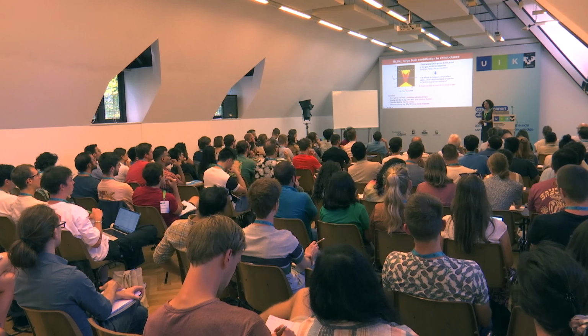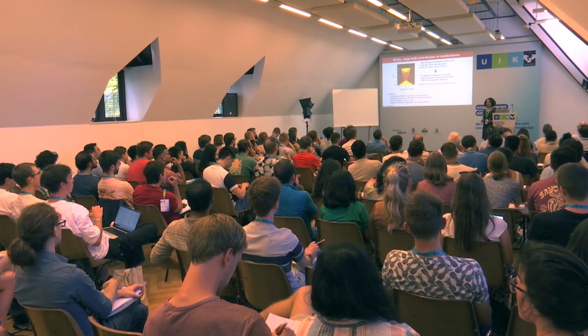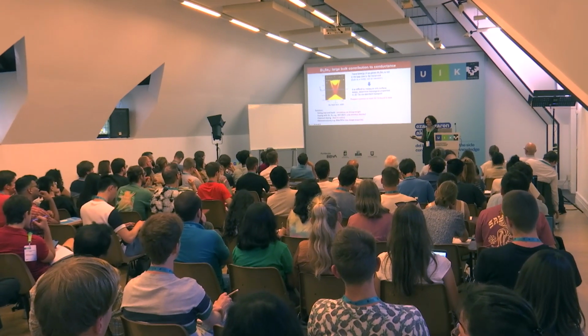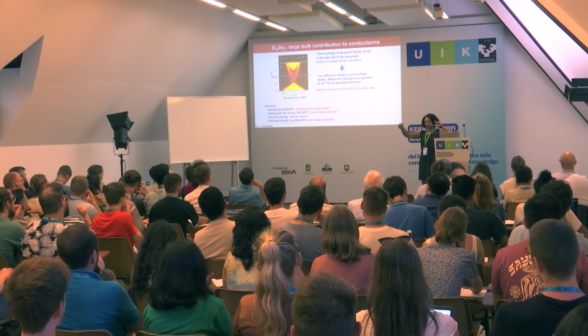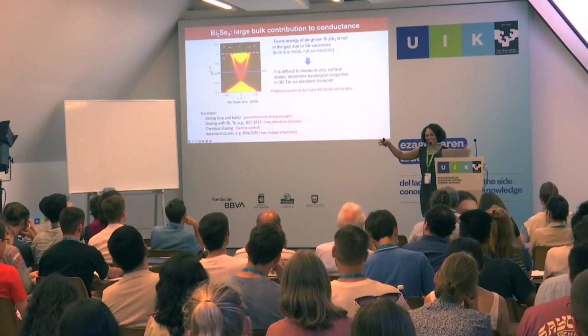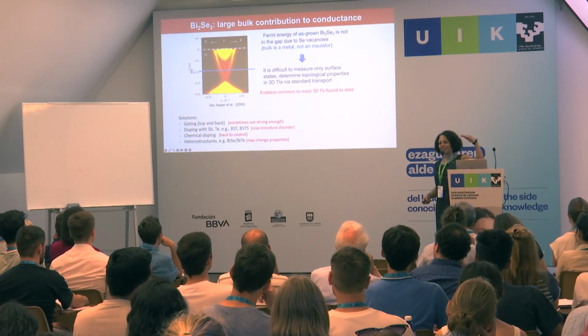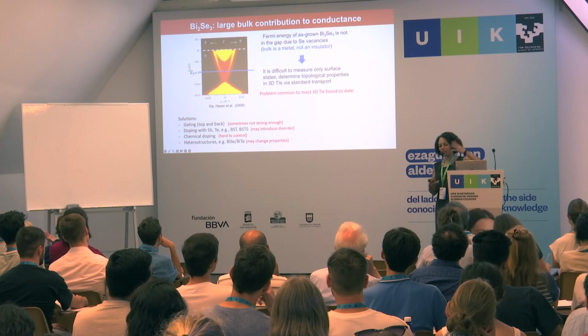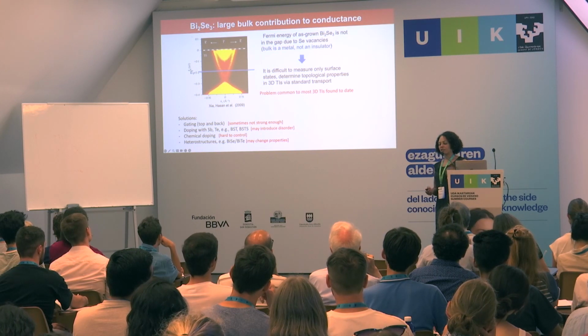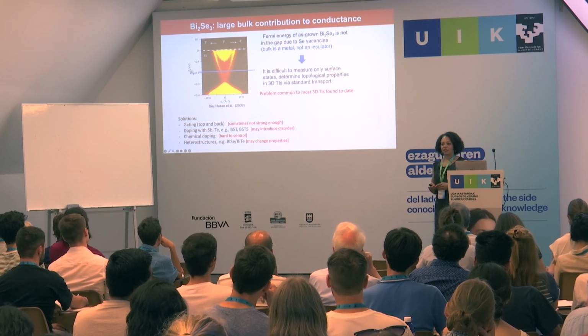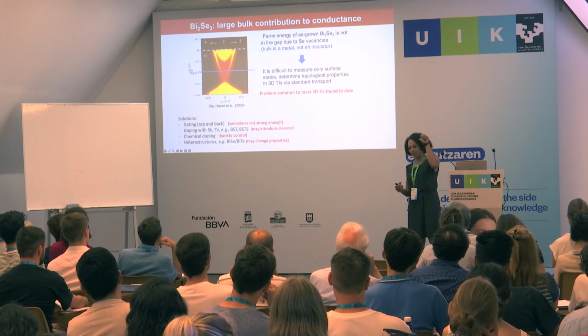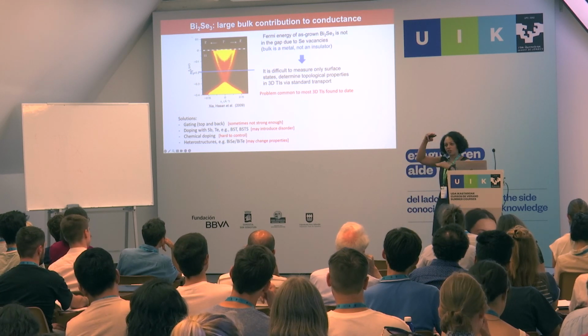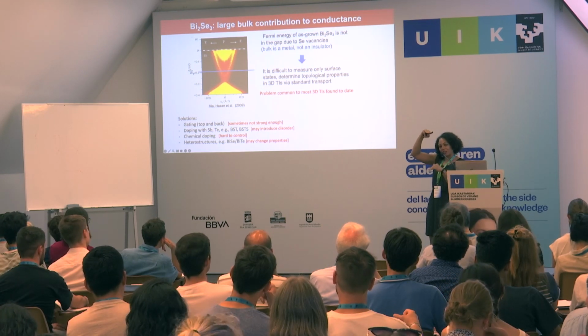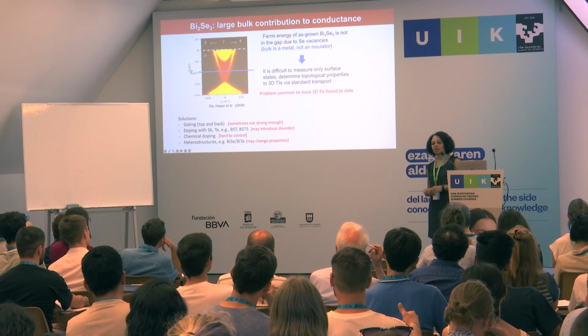Yeah, but there's a lot more of it, right? There are many electrons in the bulk. There are a lot more electrons in the bulk than there are in the surface. So even if the surface isn't as good a conductor, we're looking at resistance, not resistivity. If you're just measuring end-to-end transport, you have a surface state that's well conducting, but then a lot of bulk that's maybe not as well conducting, but when you measure resistance or conductance, it contributes more to the conductance. It's just a parallel resistor that's thicker. So you have a thick, not as good resistor, parallel to a thin, highly conducting one. But overall, even if the surface resistivity is lower, the overall resistance of the surface state is going to be higher than the bulk state generally.